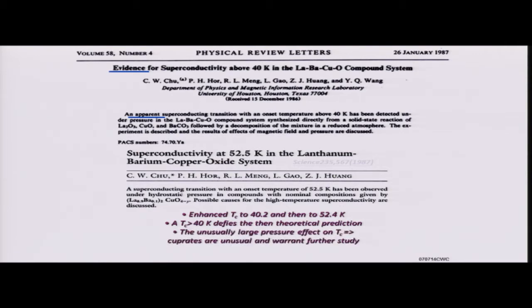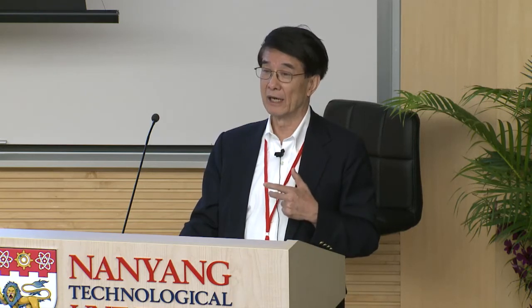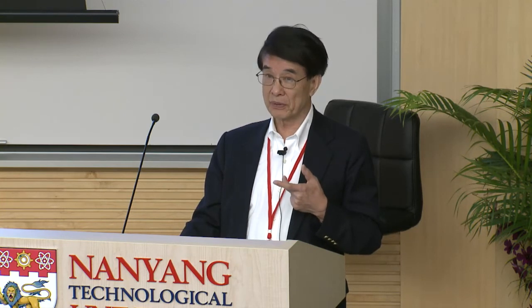And then after we raised it to 40 degrees, that was above the theoretically predicted value. But then the next thing is it was still close to the theoretically predicted value of 30 degrees. So we decided to continue to raise the temperature by the application of pressure to 52.5 degrees Kelvin. With that, there was immediately no doubt in our minds that the theoretical prediction of a ceiling of 30 degrees, or the assumption on which it was based, needed to be re-examined. And by the application of pressure, we realized the TC was raised at an unprecedentedly high rate, and therefore it tells us this class of material must be very different from the conventional class of superconductors, and it's worth further study. So because pressure raised the TC, we proposed to do chemical substitution.